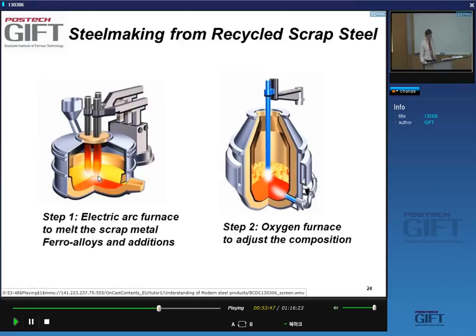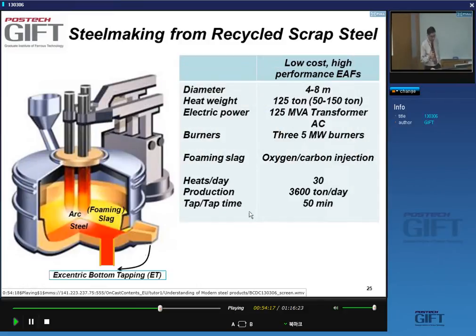Okay, so in this furnace here, we melt scrap metal, ferroalloys, and other additions, basically slag-forming additions. And of course, you need to make some adjustments to the composition, and you do that in an oxygen furnace, where you will adjust the carbon content in your molten metal by getting rid of it with oxygen. So if we look inside an electric arc furnace, we see, again, slag, which is very often called a foaming slag. I won't go into the details here. It floats on the steel, and the steel is tapped via this eccentric bottom tapping.